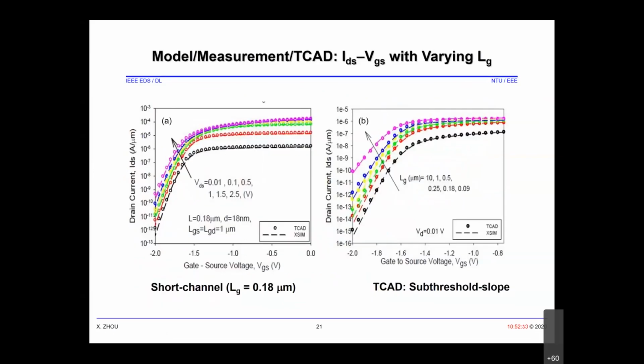Well, I won't go into model equation details, but I just show our model results in comparison with TCAD and measurement to show all these relevant effects. All the subsequent plots, the lines are based on our model, and the symbols are based on either TCAD or measurement. So these two plots show the IDVG characteristics. The left figure is for different drain bias, and the right figure is for different gate lengths from long to very short channel. We can see the subthreshold slope change, which is modeled by the thick undoped SOI based on the quasi 2D electrostatics.